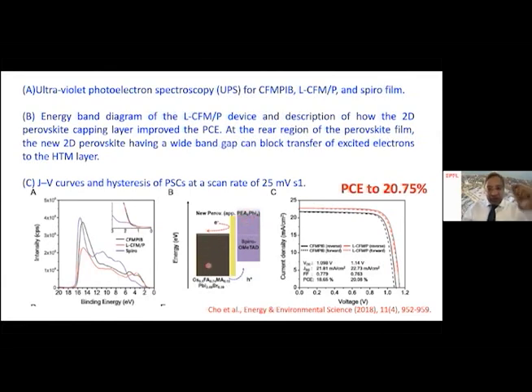Now, we are shining the light on the three-dimensional perovskite. It creates the charges, positive charges and negative electrons, and the positive charges are tunneling through the two-dimensional perovskite, reaching the hole transporting material. However, the electrons which are created here hit the two-dimensional perovskite LUMO level. Since it acts like a barrier, the electrons are driven back and they are driven towards the electron transport material. So indirectly, what we have created is channeling of positive charges in one direction and the channeling of negative charges in the other direction.